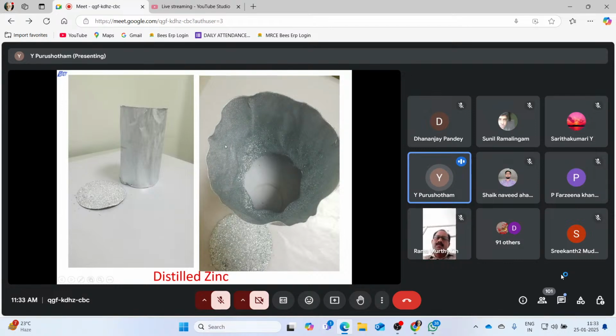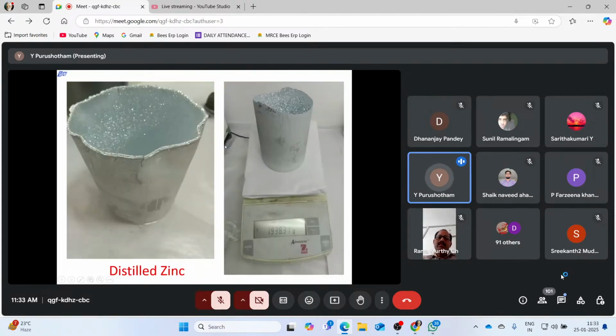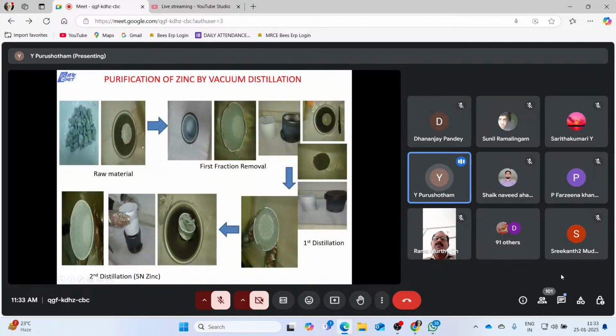This is the distilled zinc. In the case of zinc, I am telling one example, with around a 2 kg batch size. You can see here the purification of zinc by vacuum distillation. From the raw material, first we remove the high vapor pressure fraction of zinc, and the residue that is left out, we load for the first distillation.